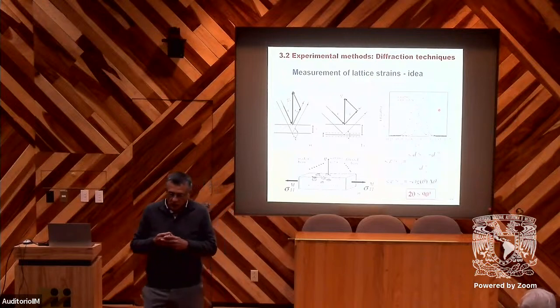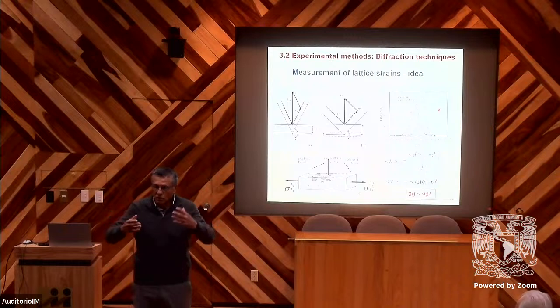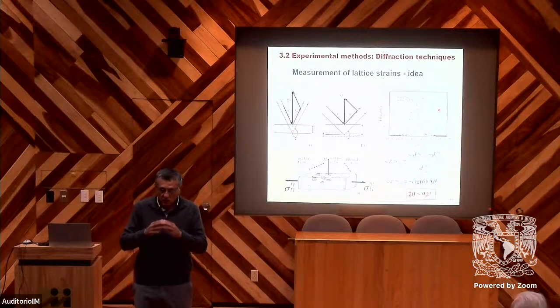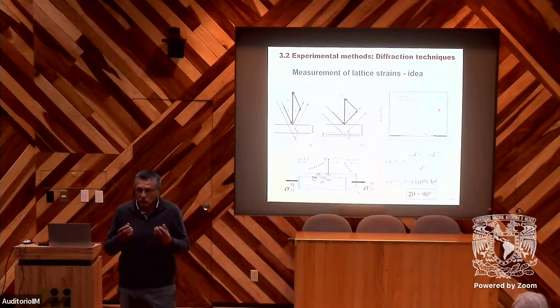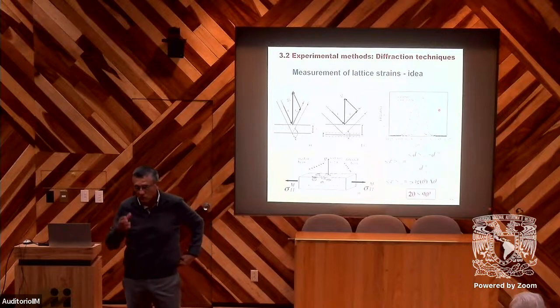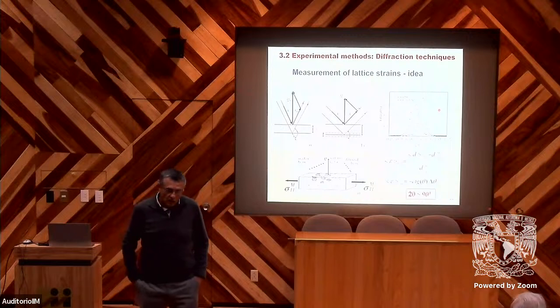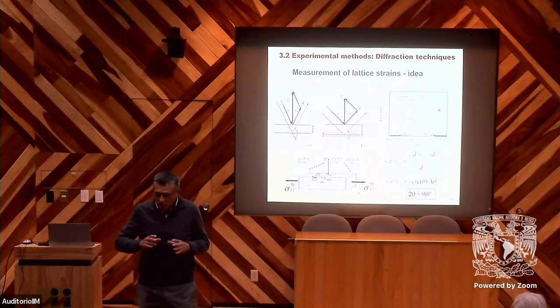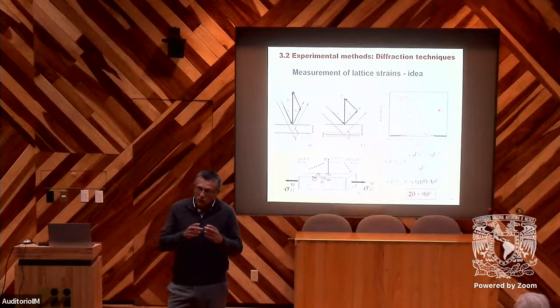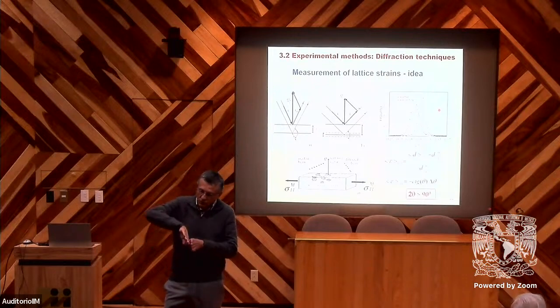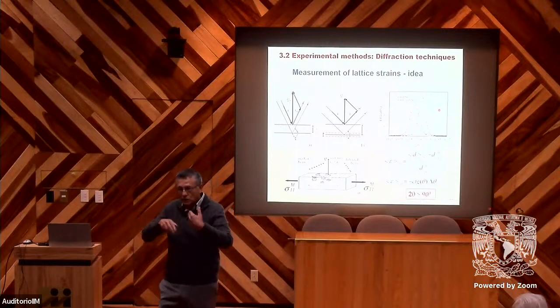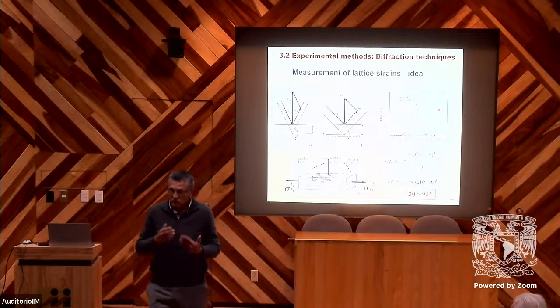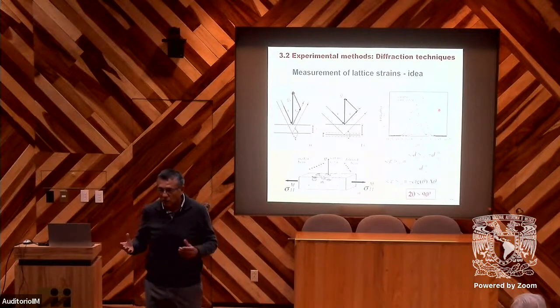But the problem is for duplex steels with thermal history and so on, you cannot say that the initial stress is equal to 0. There is some problem due to the second order stresses due to the difference of the phases. This is a big problem. For classical cases, we need D0 for neutron diffraction. We can take powder, or we can consider that we have the balance of stress, so we calculate and determine the initial D0. That means we make a correction of our measurement.